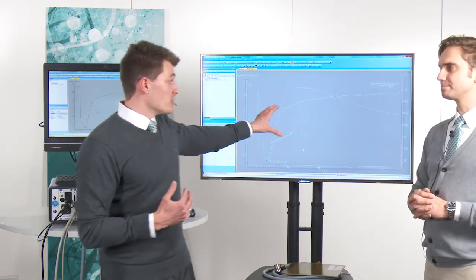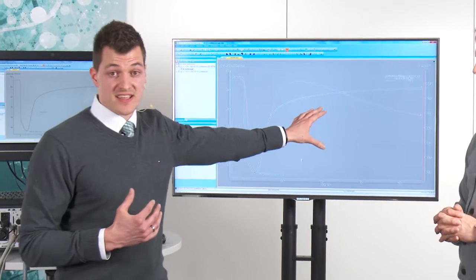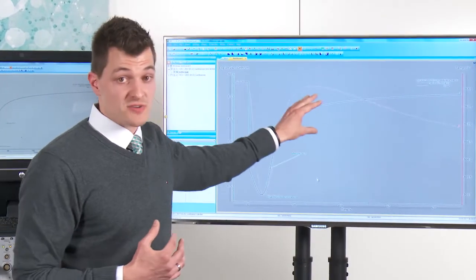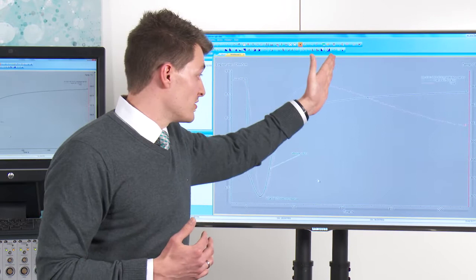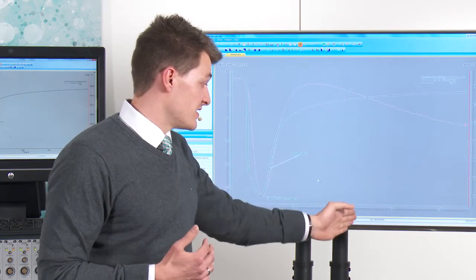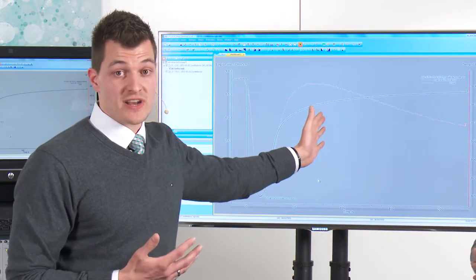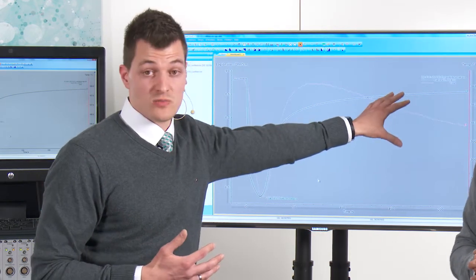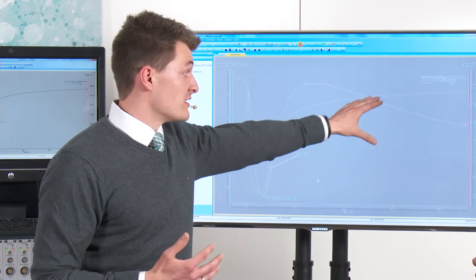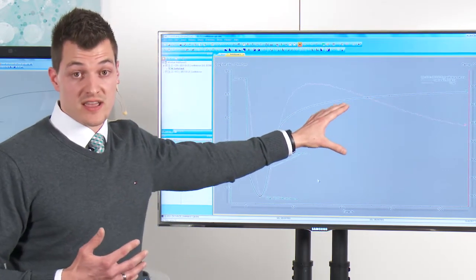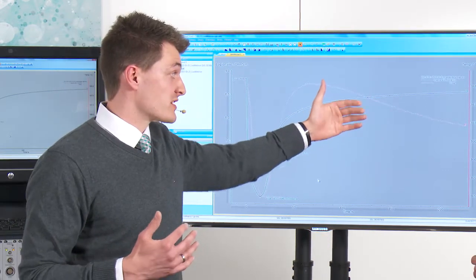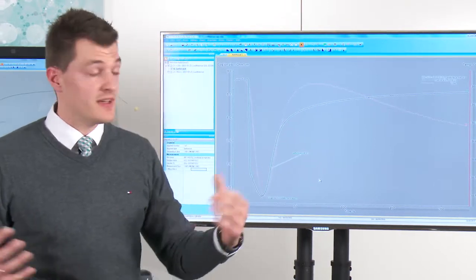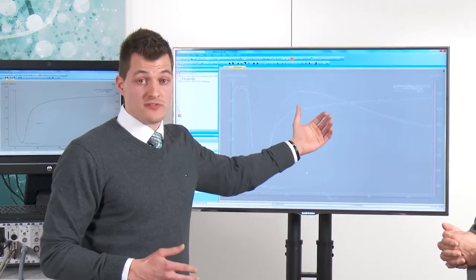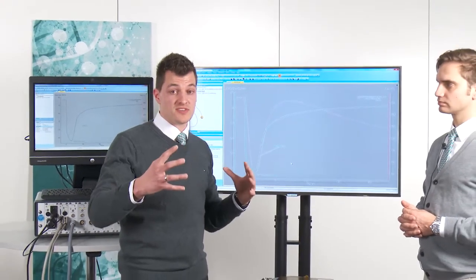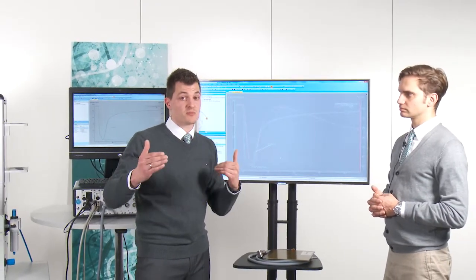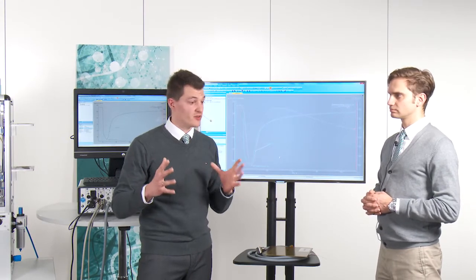If we have a look at this frequency we used here, 10 kilohertz, and for example the DSC measurement of this material, we cannot follow the heat enthalpy of the DSC after 2 minutes at this temperature of 170 degrees. But DEA can, with the 10 kilohertz curve. But also, if we cannot see any change in the 10 kilohertz curve when we reached a curing state of perhaps 95%, we can use lower frequencies to follow the post-curing process. And then we can adjust the post-curing process to see when the material is really fully cured.